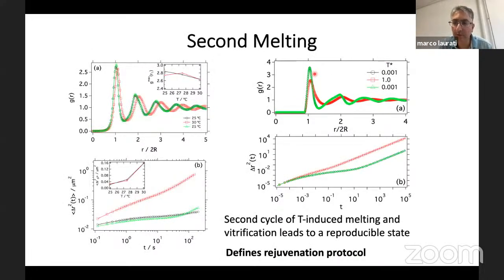And the last thing I want to show you is that the other thing that we did was repeating the melting procedure and reformation of the glass a second time. And what we found is that in this case, you can obtain effectively a reproducible glass state. So if you repeat the melting and reformation of the glass, the state is reproducible both concerning the dynamics and the structure of the system, which of course is also the case in the theory,